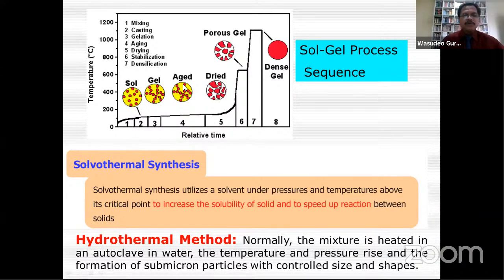Another method is the hydrothermal method. The hydrothermal method can be used to synthesize materials, and it includes various techniques of crystallizing a substance from high temperature aqueous solution at high vapor pressure. This is a method of synthesis of single crystals that depends on the solubility of minerals in hot water under high pressure. The crystal growth is performed in an autoclave, in which the nutrient is supplied along with the water. A temperature gradient is maintained, and at the hotter end, the nutrient solute dissolves, while at the cooler end, it is deposited on a seed crystal. Temperature can be used up to 300 degrees Celsius.